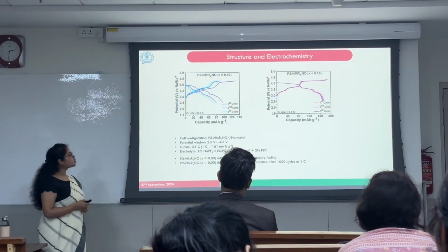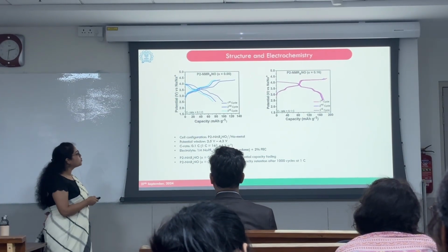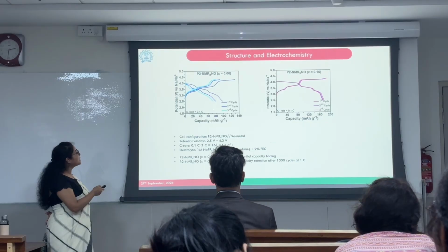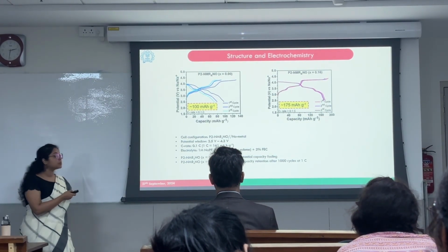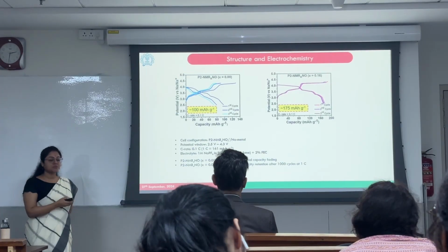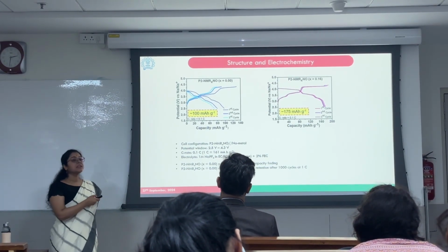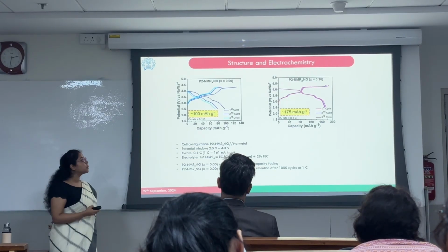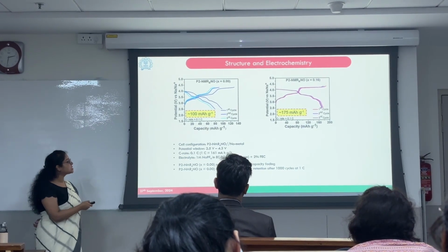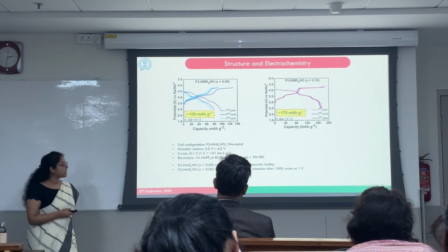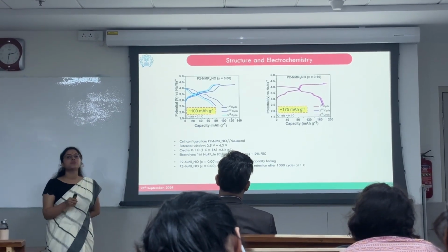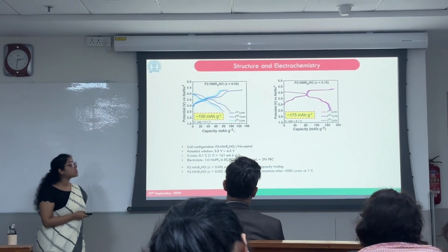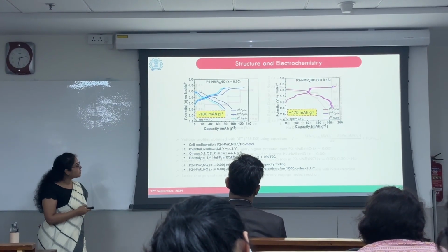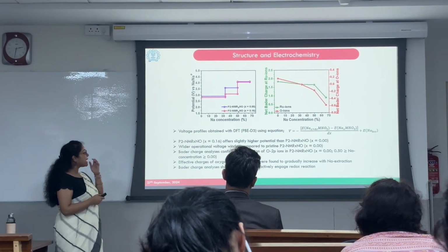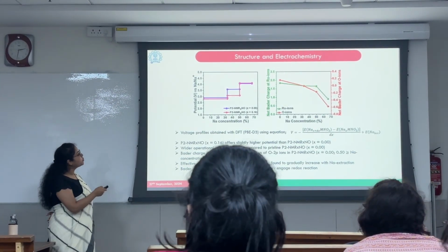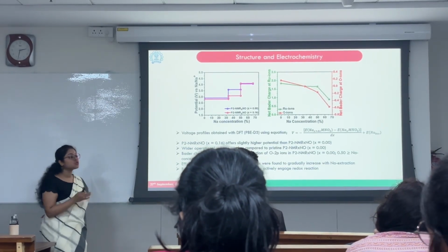So we also tested the electrochemistry against sodium metal within the potential window of 2.5 to 4.3 volt. The pristine cathode material shows a capacity of only 100 milliamp hour per gram and also suffers substantial capacity fading. The ruthenium doped one gives us a capacity of 175 milliamp hour per gram, which is higher than the theoretical capacity of 161 milliamp hour per gram. It also gives us a capacity retention of around 93% after 1000 cycles at a higher C rate of 1C. Further, we also saw the voltage profile, and the ruthenium doped one offers a slightly higher potential in comparison to the pristine one.